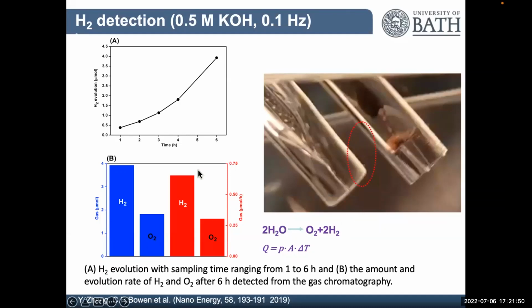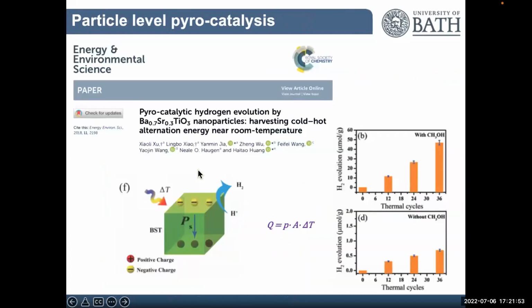They're very hard to see, but I was very excited to see that Haitao Huang, when I saw this paper, took the idea forward much better and said, well, rather than having an external device, why not maximize the area to maximize your charge by having a nanoscale material and actually putting it in the solution. So rather than an external device where A is challenging, the cross-sectional area, I just have to make it bigger and bigger by going from a dense material to a nanoparticle form. Then I'm maximizing that surface area and I'm maximizing that potential for charge generation.